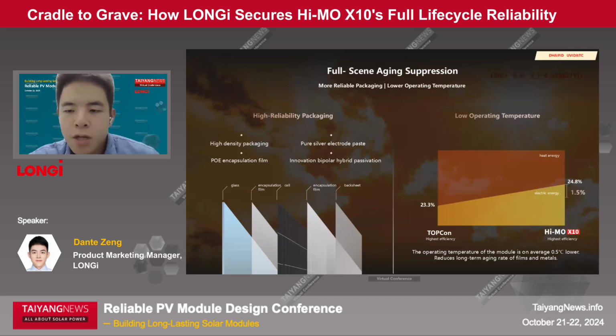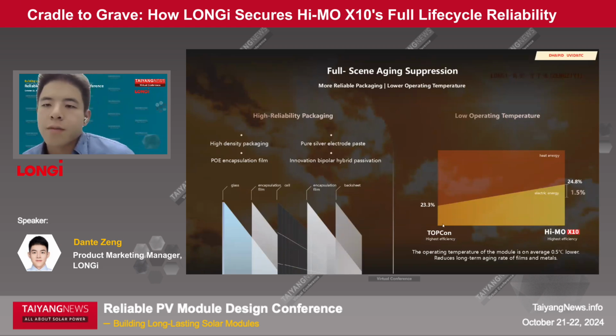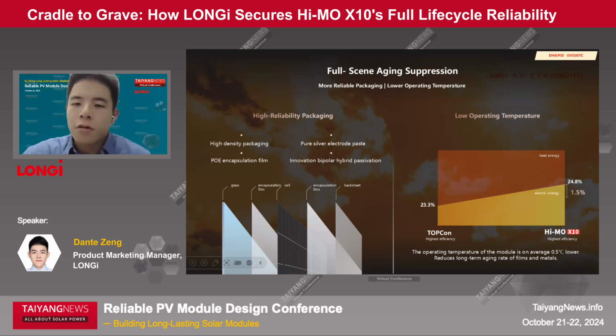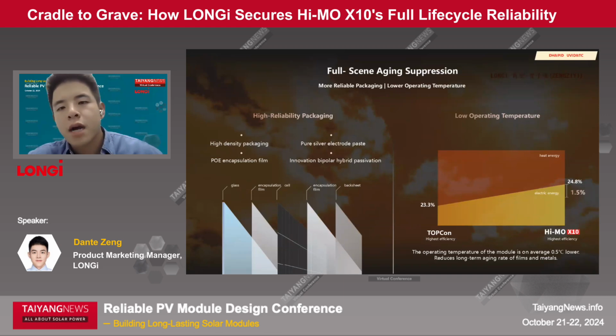And another part, I think, is a brand new finding, but it's also very reasonable, because we found in real cases, and also through theoretical calculations, that our Hi-MO X10 modules have an average 0.5 Celsius lower operating temperature than normal modules like TOPCon or HJT. We tried to analyze it. It comes from our high efficiency, because when sunlight comes into the modules, the energy divides into two parts. Around 25% will turn into electrical energy and be transmitted out of the modules. But most of it will turn into heat and raise the temperature.